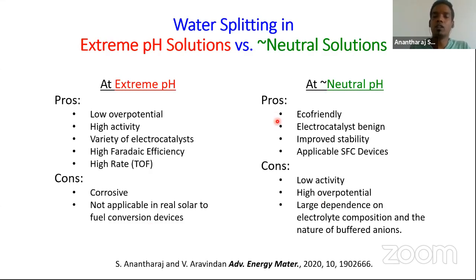So that's why people study neutral pH. Study water splitting in neutral pH. That can be exactly neutral, pH 7, or it could be closer to 7. And in literature, people defined pH between 4.9 to 10.2 can be considered as neutral, near neutral solution, and the catalyst which can split water to form hydrogen and oxygen, they can be used in solar fuel conversion devices. So these are the pros with the neutral pH water splitting.